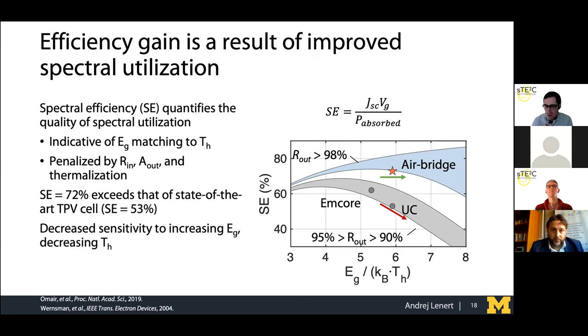So maybe we don't have access to 1500 Kelvin, maybe we can only get to about 700 Celsius in a solar converter. So it's very important to think about how we make use of these lower temperatures. And this plot shows spectral efficiency as a function of band gap divided by the heat source temperature. It's a very informative plot if you're in the field. Now, let me just explain what you're seeing here.